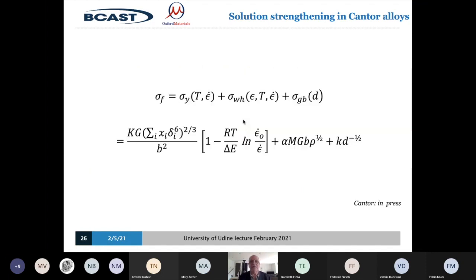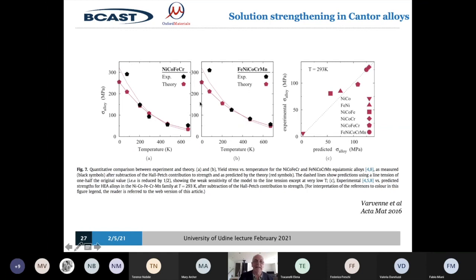The theory for this is given in this equation, which I won't bore you with in any detail, but that is the theory of what all those atoms should show. It's taken a while for us to get to the point where we could have a good theory of it. And this shows the comparison between the experiment, black, and the theory, red, for the Cantor alloy itself, and for a modified, slightly reduced Cantor alloy here. So you can see that that explanation in broad terms gives good results.